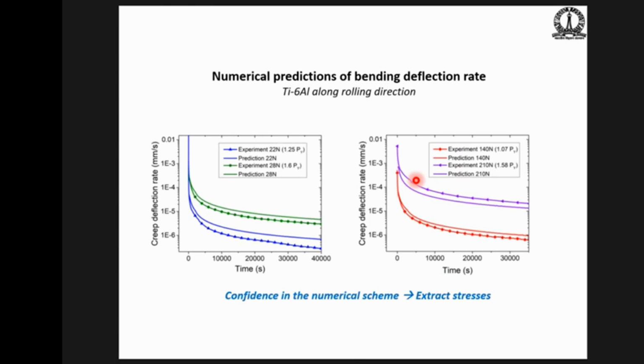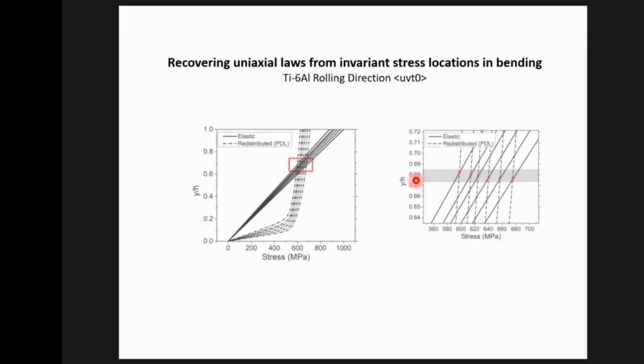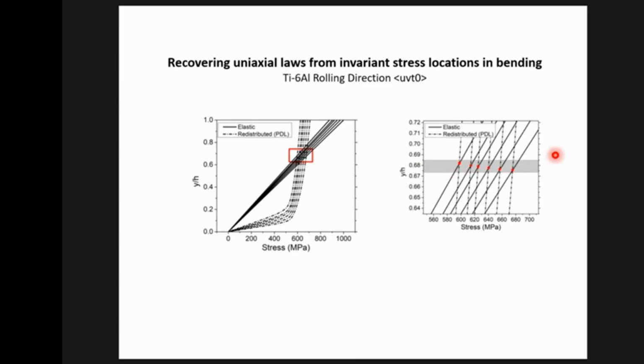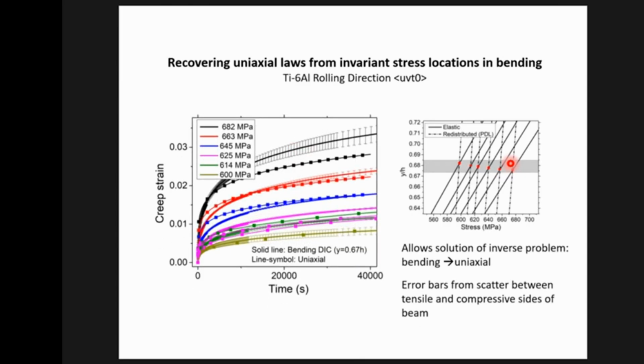So this gives us confidence that the model works, which means you can now go back and extract stresses, because the model includes the stresses and strains at every position. And if you do that, what you find is that, once again, there is this so-called invariant location. Even in the situation where you have decaying creep, you have plasticity before creep begins, and so on. So now we can go back to these locations with the confidence that each of them corresponds to a particular stress, and back out the strain rates, and then compare them with what the uniaxial strain rates will be. And this is what you end up with. I mean, given the scatter in creep, this is not too bad. So basically, you're getting multiple strain rate stress curves between 600 and almost 700 megapascals from one bending experiment.